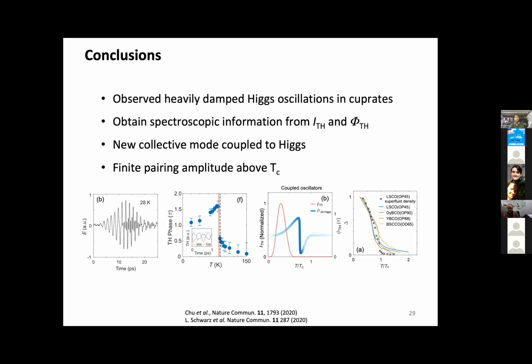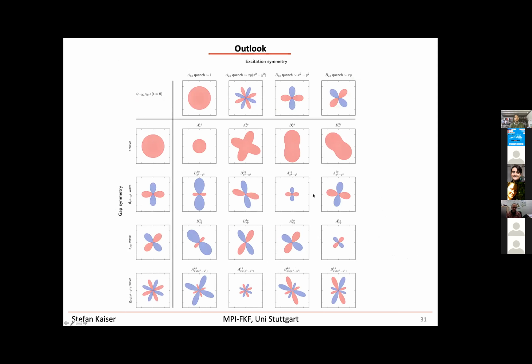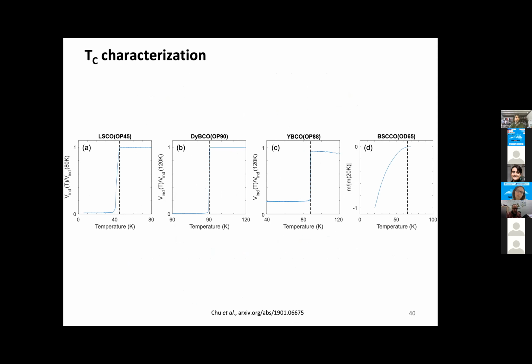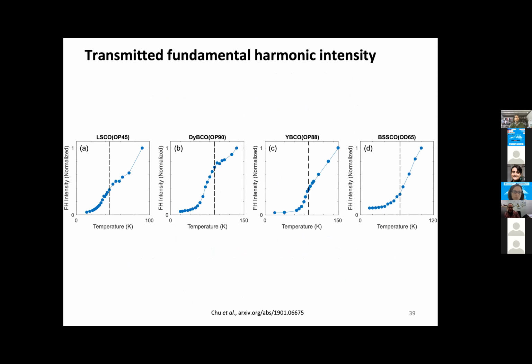phase? So one thing that we do there is, in principle, we are measuring also linear properties. For example, here, this is the transmitted fundamental harmonics, where you see strong drops at TC. And in principle, we are normalizing basically to this. But second, we also have the full linear optical properties of the material, and we can correct for this. And we have taken care that we are still in a perturbative regime, because what we don't know are, of course, the transient nonlinear optical properties in the material. So the safest way is to take the real measured third harmonic of the system. And since it's a thin film, we can assume that the local field within the thin film is more or less constant over the film, so that we don't have to take into account big changes there.